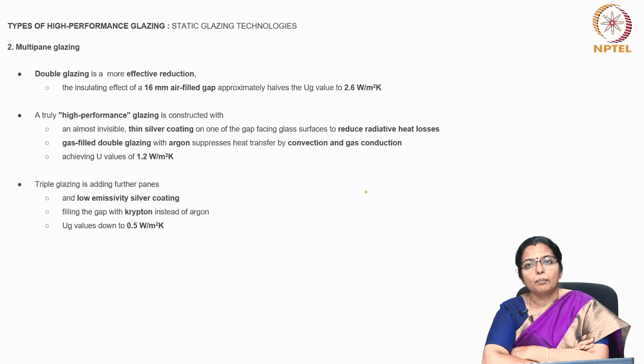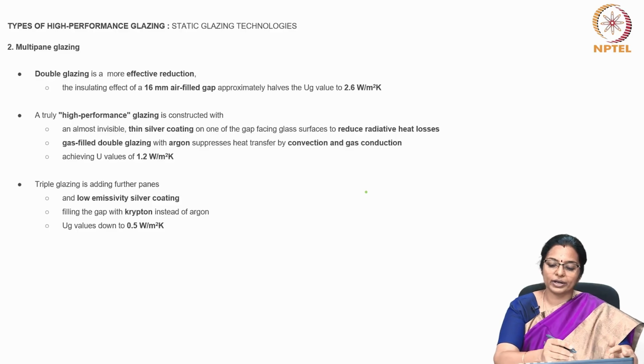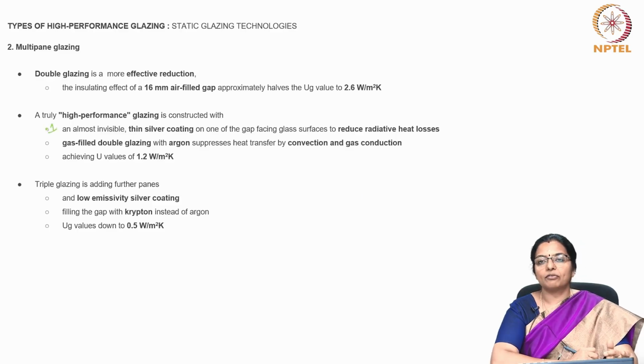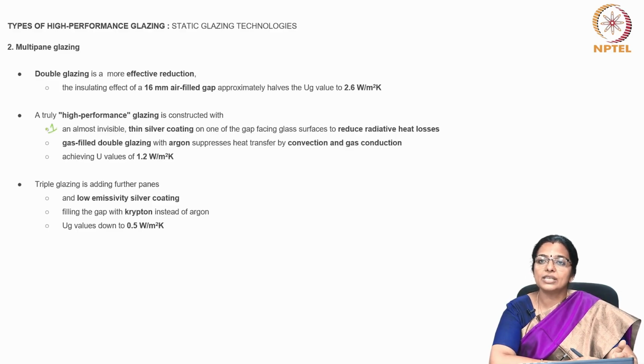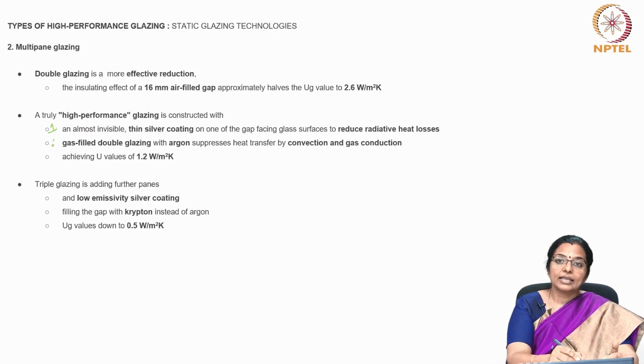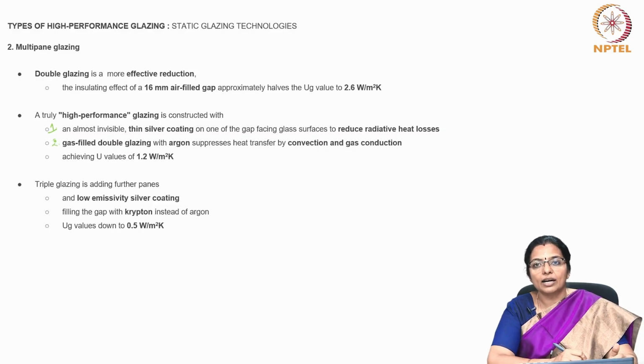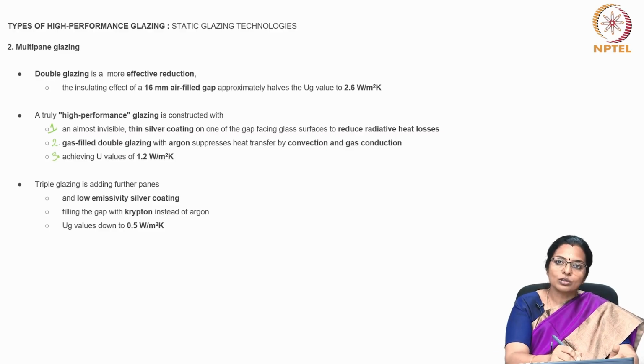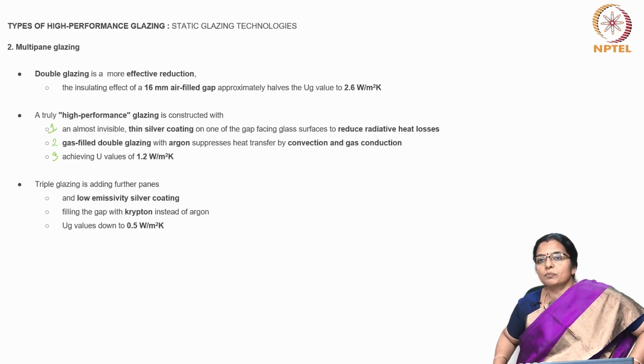Next, we will see multi-pane glazing. Double glazing is a more effective reduction. The insulating effect of a 16 mm air gap approximately halves the U value to 2.6 watts per meter square Kelvin. A truly high performance glazing is constructed with an almost invisible thin silver coating on one of the gap facing glass surfaces to reduce radiative heat loss. Then a gas filled double glazing with argon suppresses heat transfer by convection and gas conduction. This also achieves a U value of 1.2 watts per meter square Kelvin.